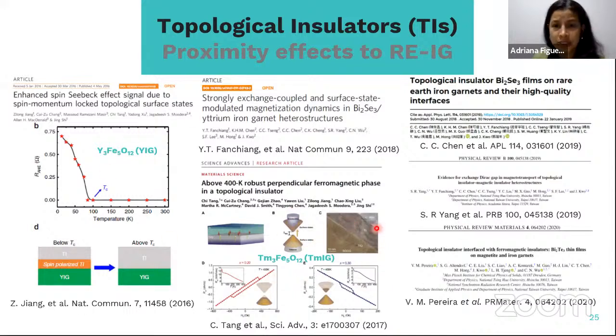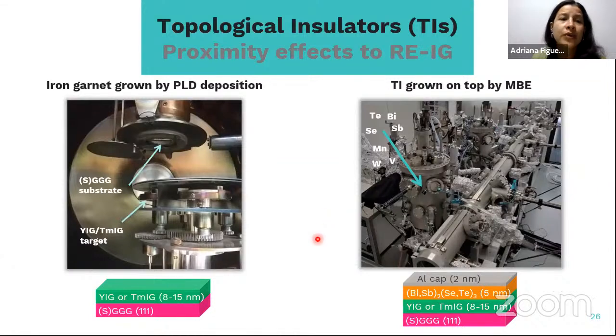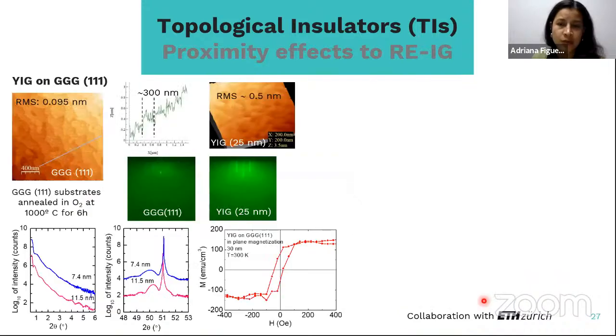And so, what we decided to do was to grow this kind of heterostructure as well, to do XMCD. So in that case, we grew the iron garnets by pulsed laser deposition in a different chamber, not in the chamber that I showed already. We grew it on a PLD system, also at ICN2 in our facilities. And then we transported those samples to our MBE system to grow the topological insulator on top. And then we end up with these stacks that I'm showing here. And then we characterize them before we do XMCD measurements.